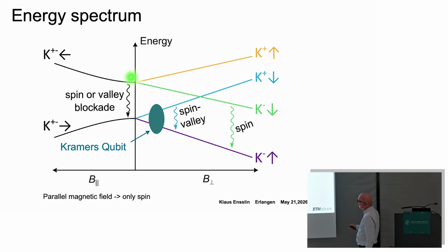So what happens is that our fourfold degeneracy is actually lifted into 2 doublets. Our quadruplet has been split into 2 doublets by the intrinsic spin-orbit interaction in graphene. And each of these doublets, you see they are funny doublets. Let's look at the ground doublet here. You see the blue curve and the violet curve, they have opposite spin and they have opposite K. It's very similar to TMDCs, where this is called spin-valley locking. And the upper state has the same thing.